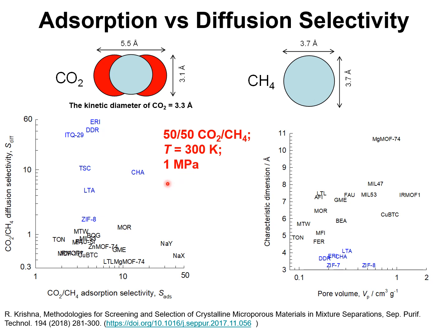Using molecular simulations of mixture adsorption and molecular dynamic simulations of mixture diffusion, we determined the diffusion selectivity for CO2/CH4 mixtures and the adsorption selectivity, for a wide variety of microporous materials consisting of zeolites, ZIFs, sodium X, sodium Y, mordenite, magnesium MOF-74, zinc MOF-74, copper BTC.